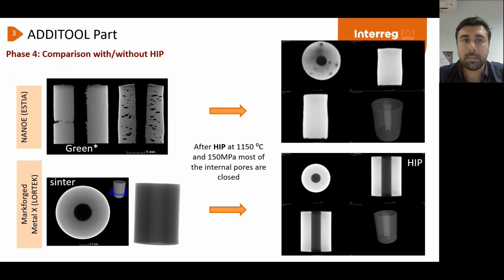And after HIP, so hot isostatic pressing, at more than 1150 degrees and 150 MPa of pressure, most of the internal pores are closed, for the Nanoe filament as well as the Markforged. So this is something that can replace a mechanical force for the sintering. You can have access to a HIP.